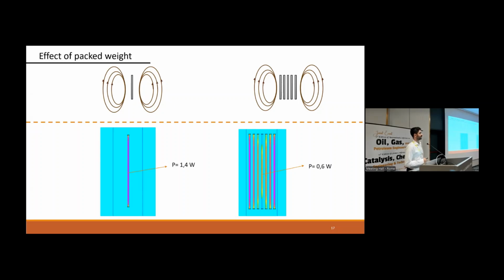And why is this really important? Because if you imagine doing any type of scale-up later for the reactor, we really have to take into consideration that the heating is not homogeneous radially. So we're going to have a heating that's stronger on the outside radius than in the middle of our reactor. So that's really important.